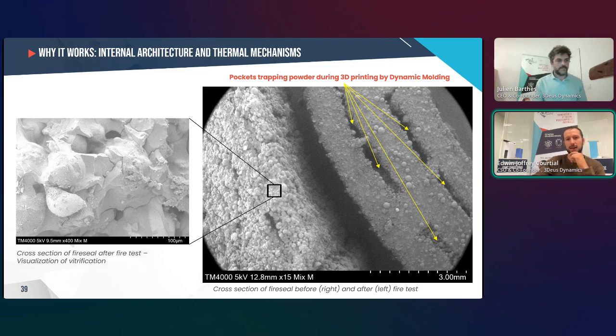The mineral powder has undergone a partial sintering and vitrification process. The spherical particles have fused locally, creating a continuous glass-like crust that seals the outer surface of the joint. This vitrified layer acts as a self-formed thermal shield, drastically reducing heat transfer and preventing oxygen diffusion towards the inner